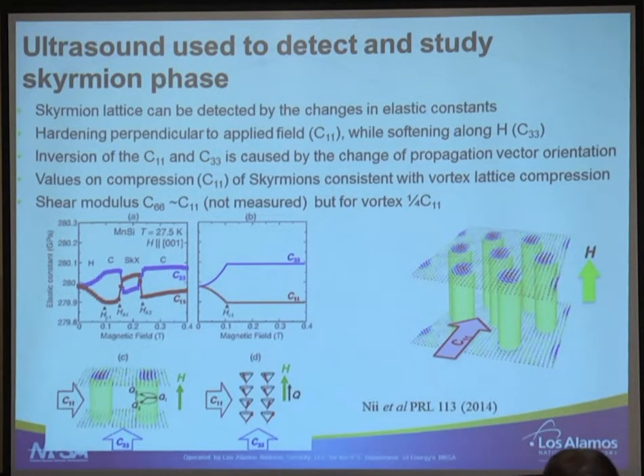So why do we want to do this with Skyrmions? Well, a couple of years ago, my coworkers and I showed that by measuring sound speed, they could see the changes on entering the Skyrmion phase. You start at zero field, and you see the splitting. When you have a cubic system and you put a magnetic field, this breaks the symmetry. So you have C11 and C33. C11 is the compression of vortices against each other, and C33 is the compression along the direction of the magnetic field. And when you see that, you see the split.